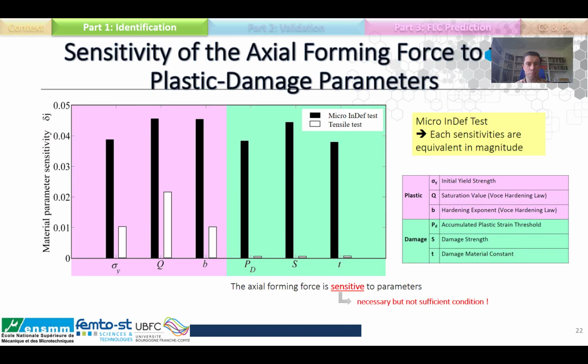Now we have the identified parameters. The question is, do we have the good ones? Are we sure these parameters are not just some values from mathematical fitting? If they are, then our chosen method is not good to validate the constitutive model. Another question we can ask is, do we really need to use the Micro InDef test instead of just a tensile test to obtain these parameters? The first step to answer these questions is to be sure that the forming forces, namely Fz, depend on the material parameters, which means that with the modification of material parameters, the forming forces will also be modified.